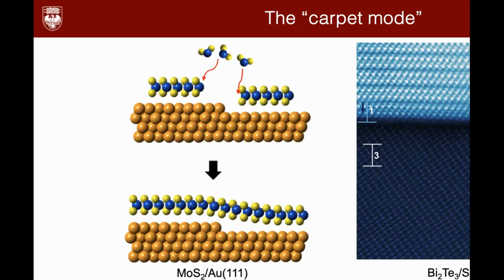Normally for epitaxial growth, just for everybody's information, there are step terraces on the substrate. And usually if your film is epitaxially strained, then it should actually have breakage near the step edge. But this one, instead of having a breakage, if you pay attention to the morphology of the film, it almost hovers above the substrate surface, forming an almost freely floating morphology. So it's a very special type of film that extends coherently without disruption by the substrate step edges.